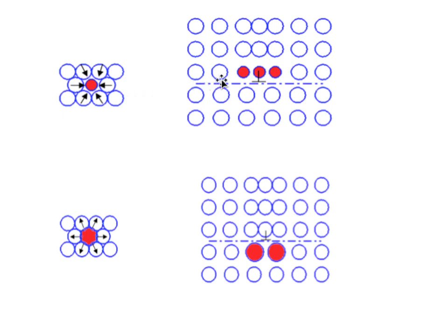And if you look into what may happen when a dislocation is moving close to these alloy elements, we can see here that it will start to interact with the alloy elements. As the alloy element is a disturbance in the crystal lattice, and the dislocation is also a disturbance, they tend to cling to each other, and in that way they can minimize the total disturbance in the system. So alloy elements tend to line up and decorate the dislocations, and in that way they also lock the movement and the slip of the dislocations. It happens both for smaller atoms and for larger.